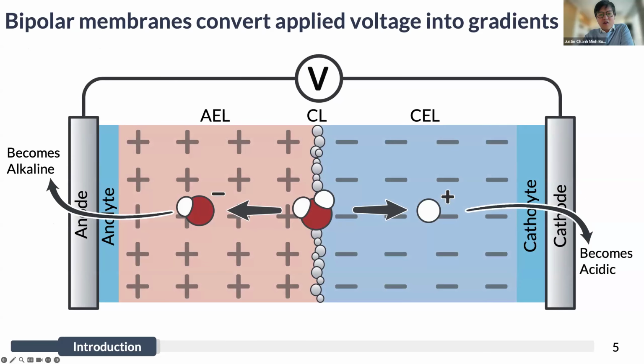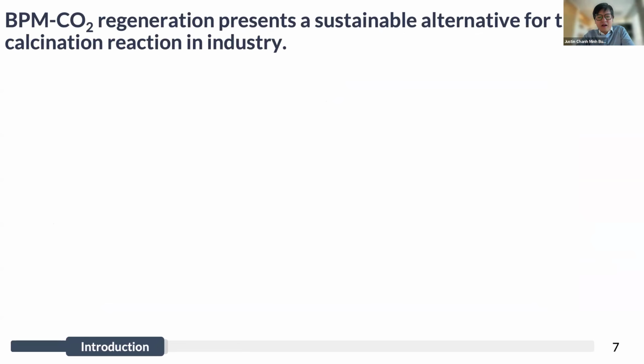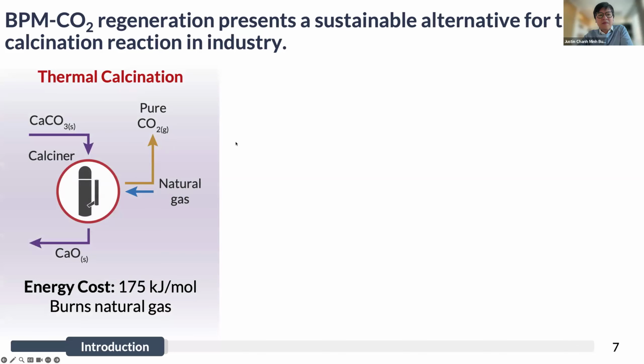And this results in an overall pH gradient that is developed that is directly proportional to the amount of voltage that I've put into the system. And so this tells us that we can use a bipolar membrane to convert electrical energy into a gradient in pH. And there are a lot of interesting applications for this type of chemistry, but the most interesting one, at least from the perspective of industrial chemistry and carbon capture, is the ability to replace the industrial calcination reaction.